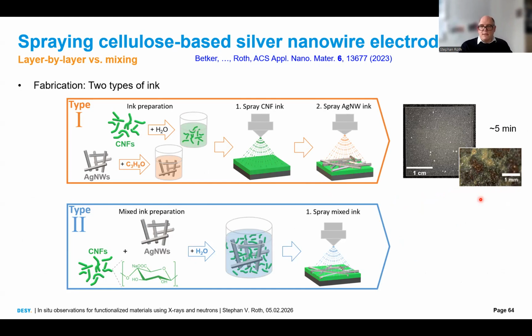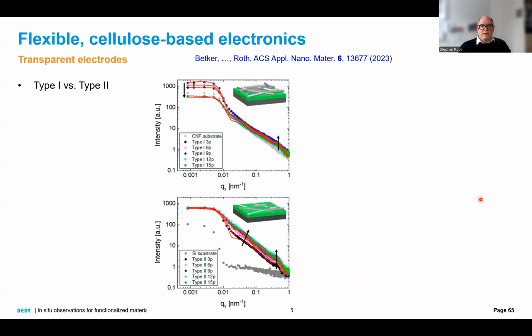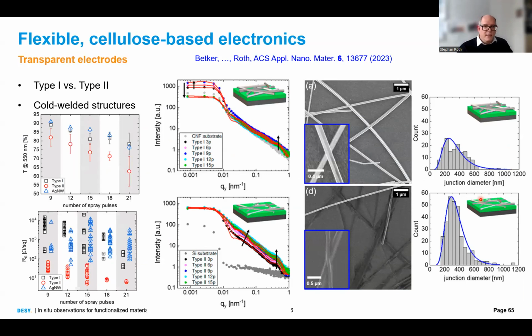What you can do is you can use silver nanowires. You can spray them on your paper, or you mix with cellulose nanofibrils and you spray the mixture. And always my question is, it's somehow counterintuitive. When I add an insulator to a metallic mesh, it should become less conductive. And if you look, however, I just go through here. You see here this type 2 electrode. This is the mixed cellulose silver nanowire electrode. It has a lower transmittance than the pure silver nanowire electrode or silver nanowires on top of CNF, but it has a much lower sheet resistance. And the question was, why?